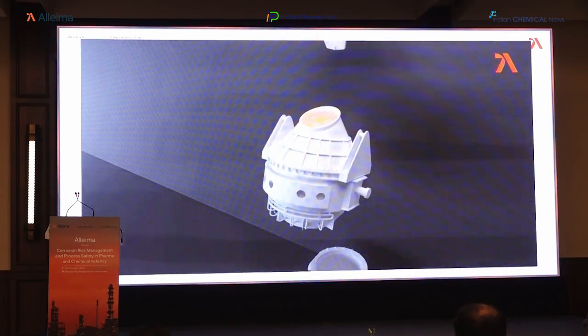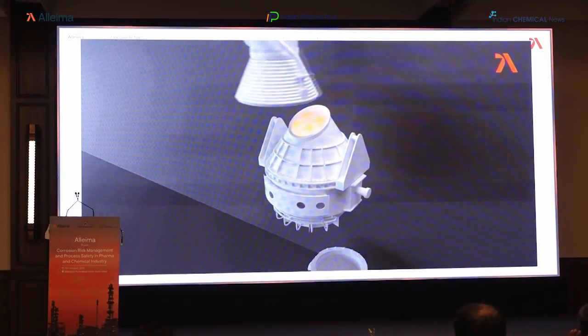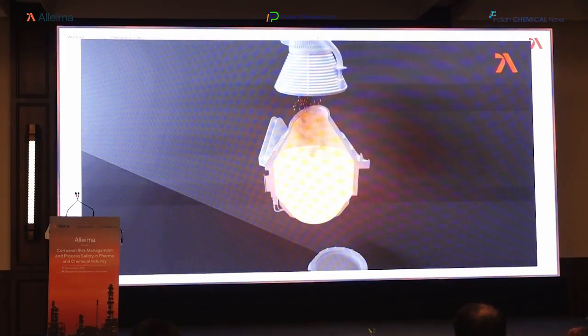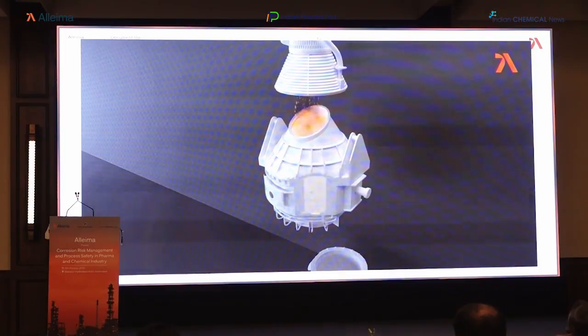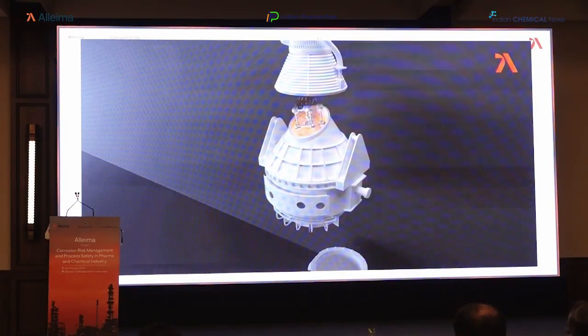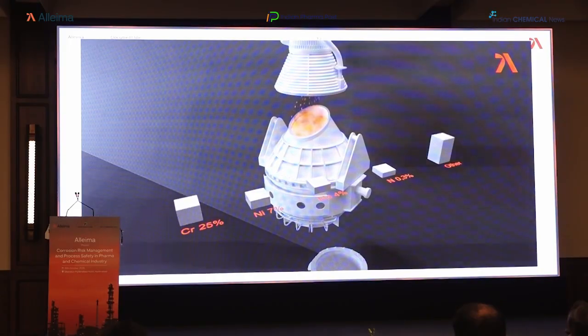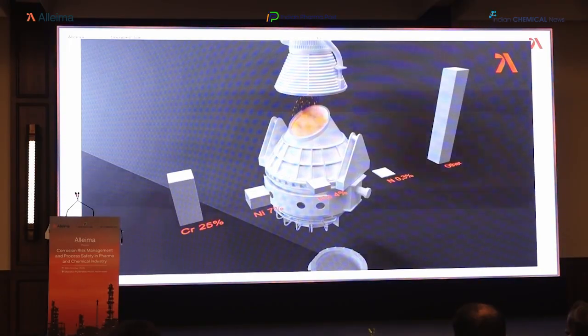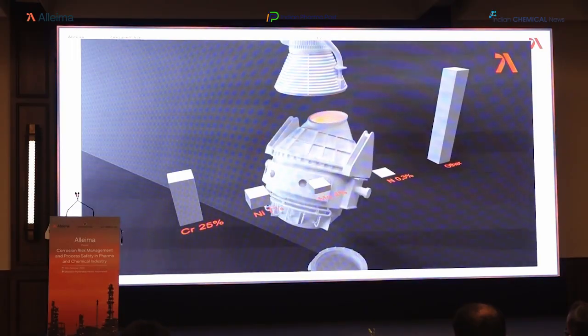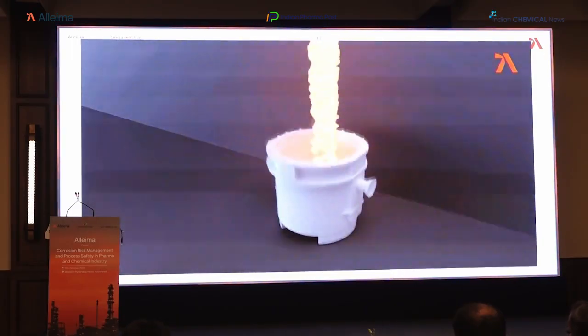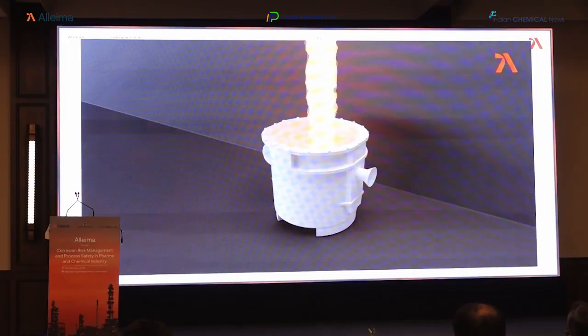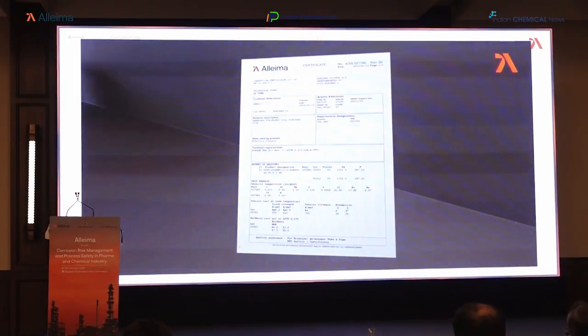Exhaust gases from the furnaces and AOD processes are filtered to cut pollution, and the dust extracted is further processed for metal recovery. The chemical composition of the melt is closely monitored throughout the process to meet our own demanding standards. We make continuous analysis to guarantee the correct steel grade and ensure traceability and consistency between the batches. The results are entered in a form that accompanies each batch at every stage of the process.